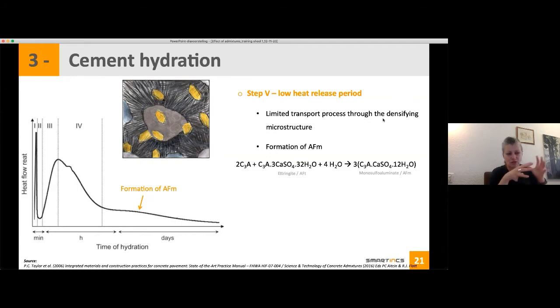I mentioned before that you don't have sulfate anymore, but if you still have some C3A inside your system, this can react with your ettringite, and then you can form some monosulfoaluminate. And this you see because you have a small bump in your curve. That's also where you have your C2S and ferrite that will hydrate. So they are there in your cement particles initially, but in the first hours, they won't do much or not contribute a lot to your cement hydration.